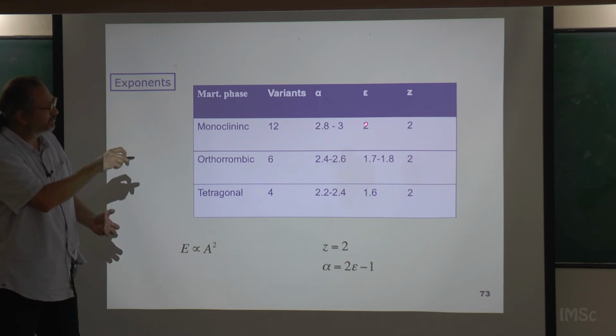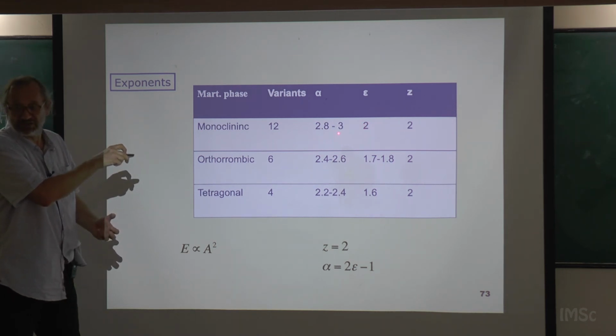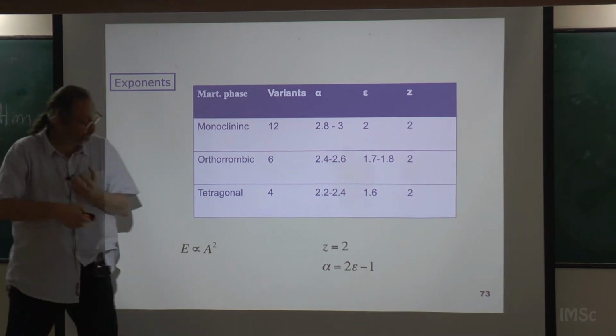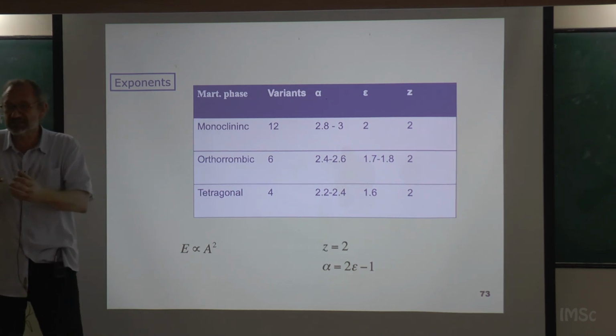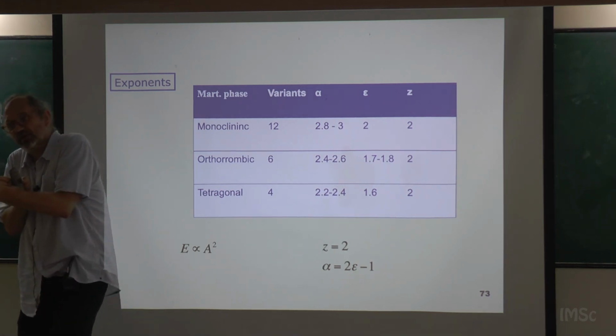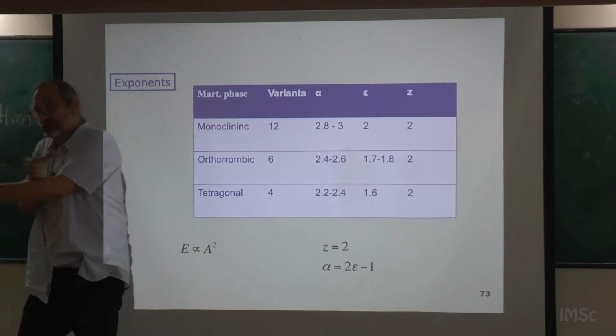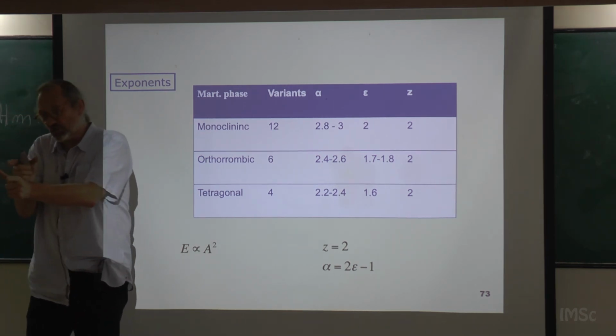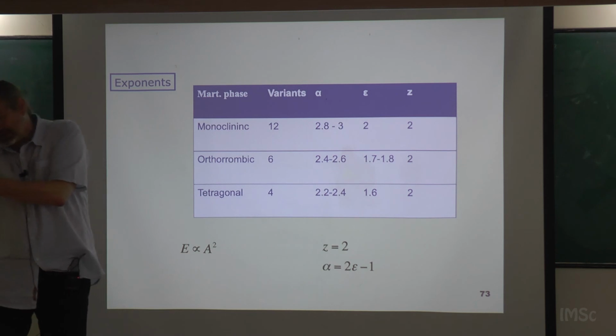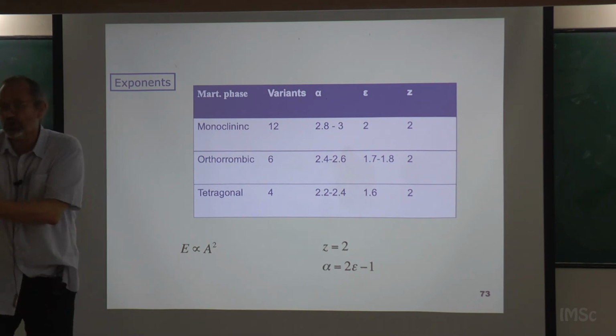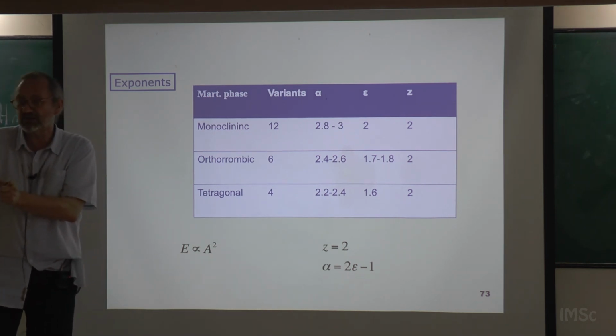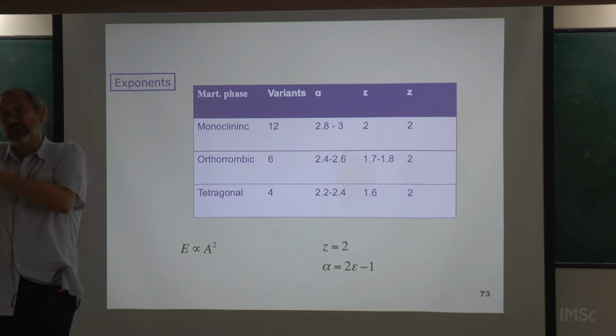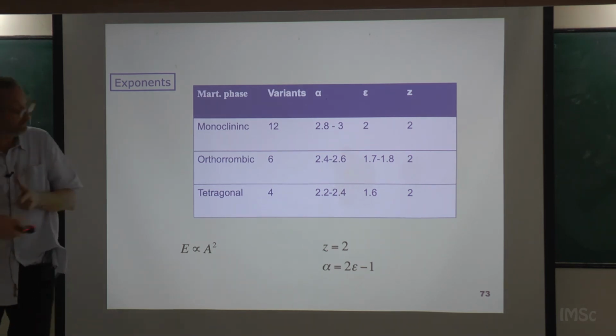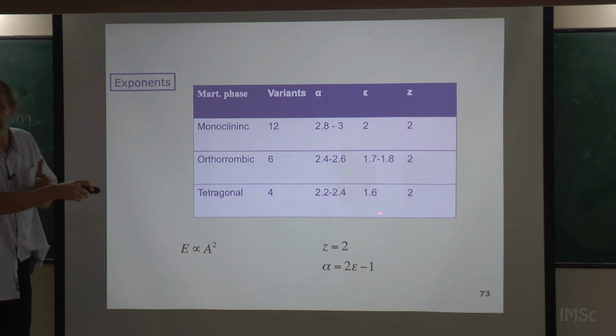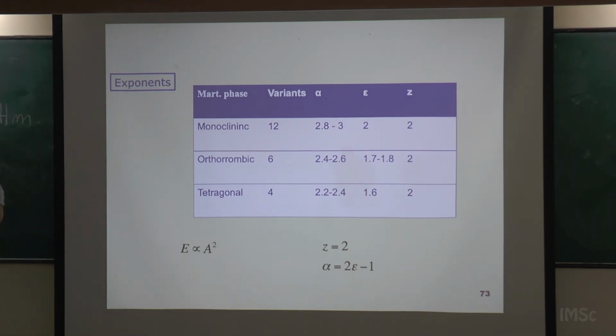Okay? Too for energies. When you have fewer possibilities, the system is forced to wait until it can grow in that direction, because there are only 3 possible directions to grow. So it has to wait until it can relax towards that path. It cannot do another thing because there are only 3 ways of advancing. And this forces it to have larger jumps, and then you get lower exponents. So the exponent changes with the symmetry of the low temperature phase.